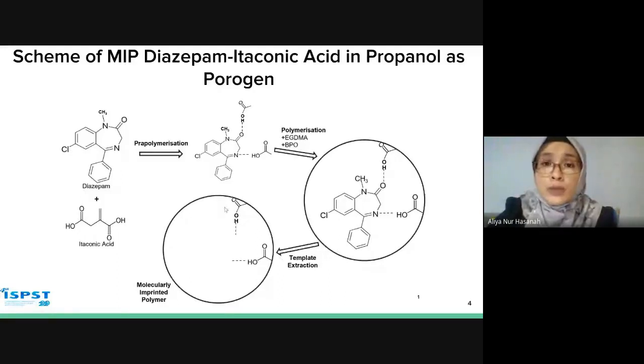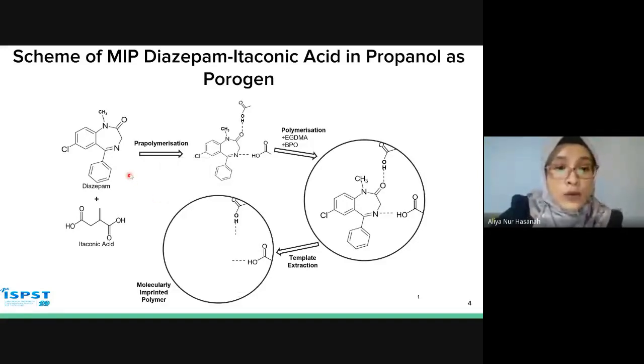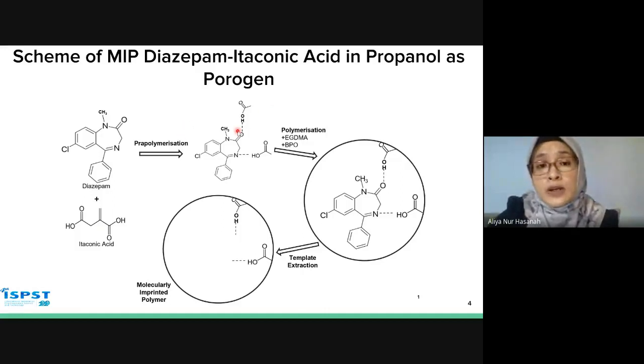As a general scheme, when we want to synthesize the MIP, we have to have a template, which is the diazepam that we use, and then itaconic acid, the functional monomer. We mix them together with propanol as a porogen, and then mix again with EGDMA, which is the crosslinker, and BPO as initiator to initiate the polymerization.